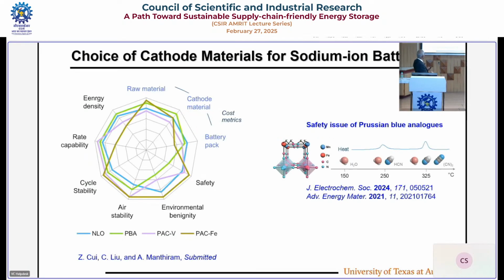So there are three possibilities: layered oxide, Prussian blue, or polyanion. Prussian blue can have safety issues because when temperature is increased, you can have hydrogen cyanide or cyanogen evolved. Cyanogen is worse than hydrogen cyanide. It can kill people. So it's very hard safety-wise. The polyanion has lower energy density, so layered oxide may be the best.